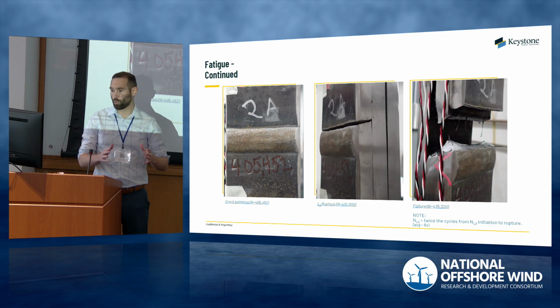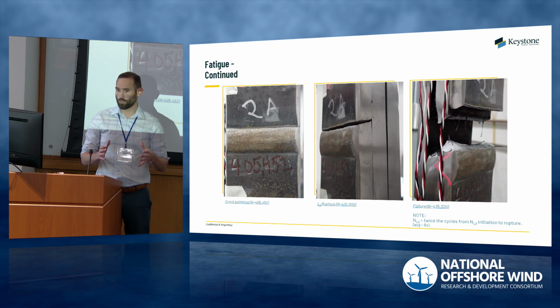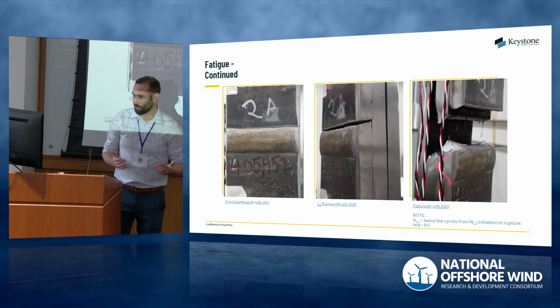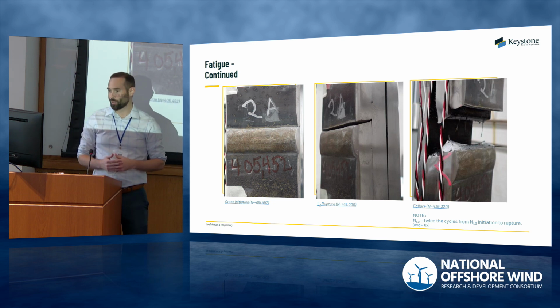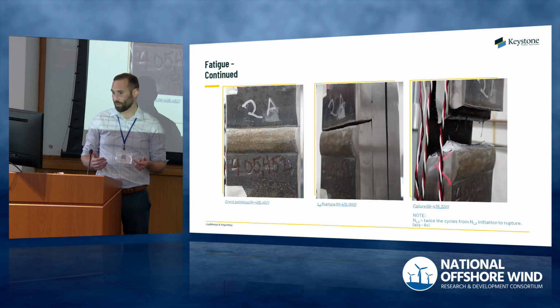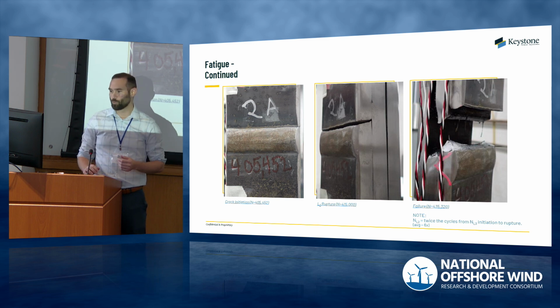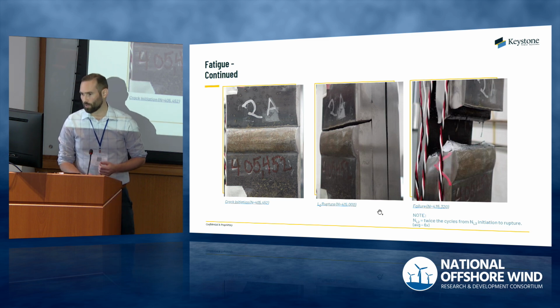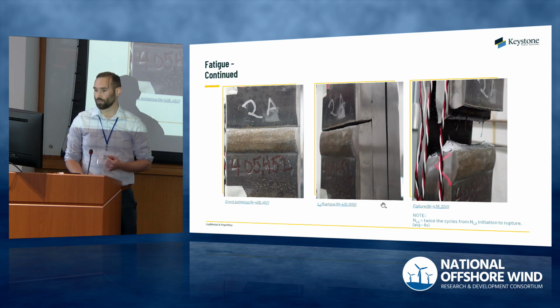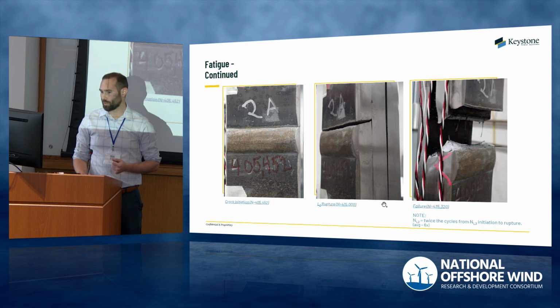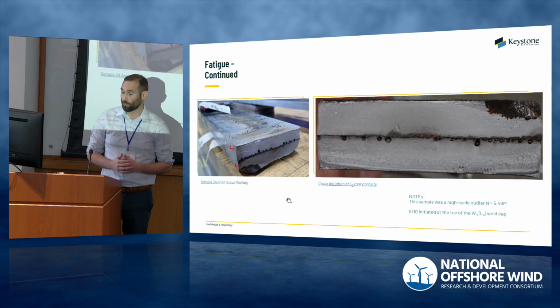I think the important part of this is once the structure is deployed, you'd be able to observe, through accelerometers and instrumentation of the turbine, degradation in the stiffness of the tower. You'd then be able to halt the turbine, put it in park, and deploy some O&M, maintenance, to go look for cracks, find them, and repair them, and not have catastrophic failure of your tower. You'd have a resilient system that's robust against catastrophic failures of this sort.